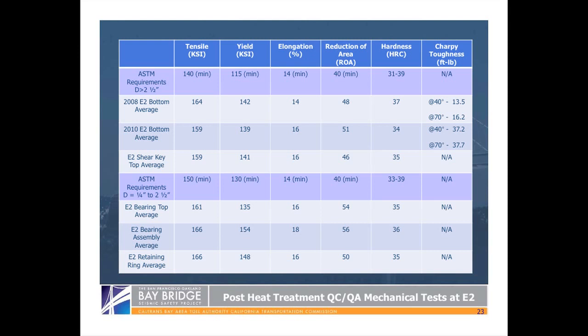And you can see, Peter, if you'll help me with the cursor again, right below the 2010 bolts, you'll see the E2 shear key bolts, and again, you will see a hardness value that is more consistent with 2010 than with 2008. And if you go down the list, you will again see values, most of them closer to 2010 than 2008. The reason we have two ASTM standard rows on this chart is because they have a different standard the bigger the bolt. So the big bolts are on the top, greater than 2.5 inches in diameter, and the smaller bolts are on the bottom.